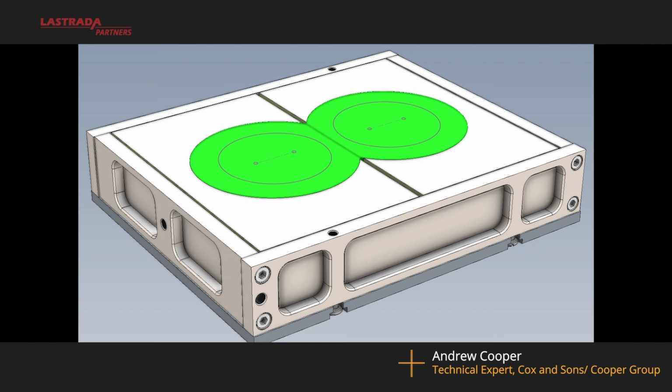And not only that, but if you do your test at the moment, you take the combination of 2 pucks together and say this is one side, and the combination of another 2 pucks together and say this is the other side. If there's too much of a gap between the deformation of those 2 results, you have to discard the results, because you do not know which one of them has performed badly, so you can't retain a result. If instead you looked at all 4 of those pucks as individual pucks, and you saw that one of them was the outlier, one of them had deformed more or less, if you had aggregate interlock on one and pieces of aggregate sitting on top of one another, and this didn't allow the puck to deform, for example, you could extract that and you still have 3 results from which you can take the mean, and I think it's a much better way to analyze the data.